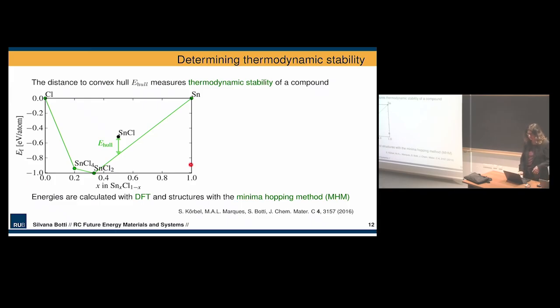And I show here an example in 2D, so this is easy to see. When we go to higher dimension, it becomes, of course, harder. So we have chlorine and tin in their most stable form, and here, of course, we are at 0 Kelvin, so we are looking at crystalline forms of this chemical element at 0 Kelvin, and a similar thing can be built if we include temperature and pressure, making instead of the formation energy, the Gibbs free energy.